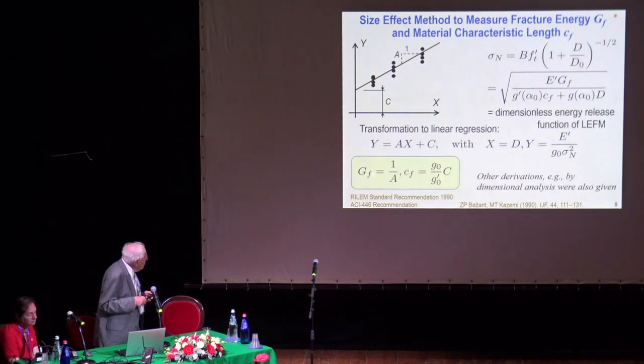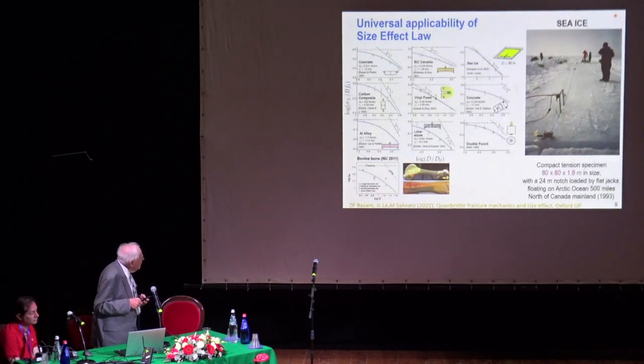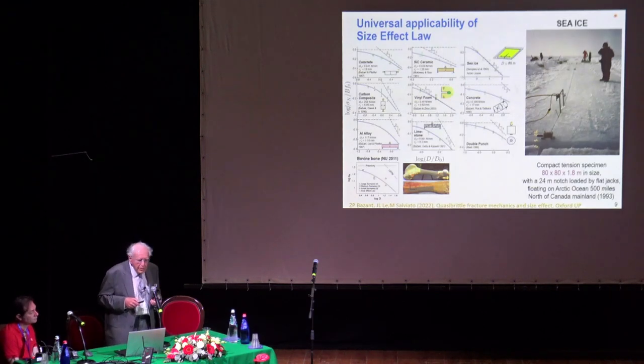From that, you can get fracture energy, and also the width of the fracture process zone, which is, in fact, the easiest way to obtain these parameters. Now, this formula was first developed for concrete, but then it turned out that it works for all quasi-brittle materials, which are coarse-grained ceramics, fiber composites, all kinds of rocks, many materials. And there are many diagrams like this. This is only a fraction of what we have.